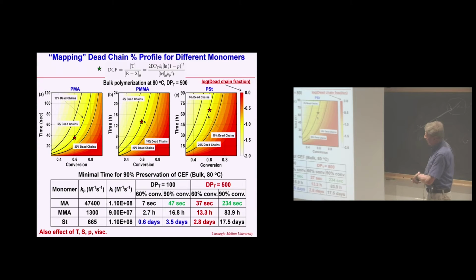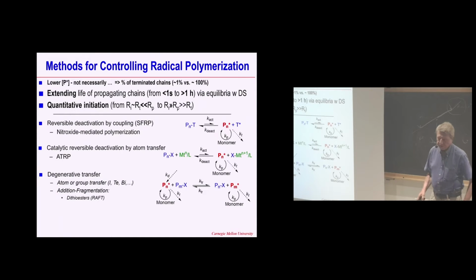So therefore, if you would like to have, let's say, degree of polymerization 100 at 90% conversion with 90% preserved chain end functionality, you can run this reaction at 60 or 90% conversion within seconds. But here you need hours or maybe even days. So this is important. If you would do these experiments, you need to know what kind of monomer you have, what propagation rate coefficients you have, and how to control these reactions. So in principle, you may say that you need low radical concentration in order to have a controlled radical process. But in reality, it's not only radical concentration, but it's the fraction of terminated chains. So for what I showed you, acrylates or acrylamides, you can have still fast reactions and very few terminated chains.